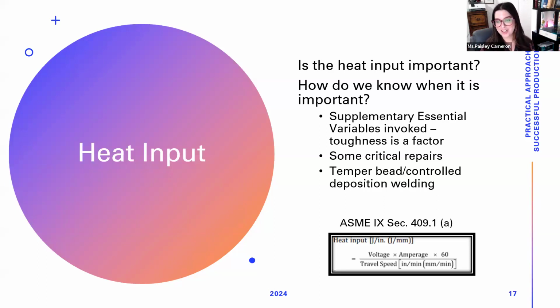So this may not just be the application of low temperature, just as we saw on the slide prior, which is a high temperature application, which is a high nickel chrome alloy, which you typically wouldn't have an issue with cracking, but in that case you did. So toughness is very important.